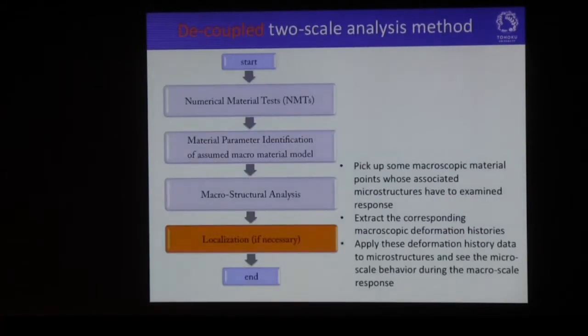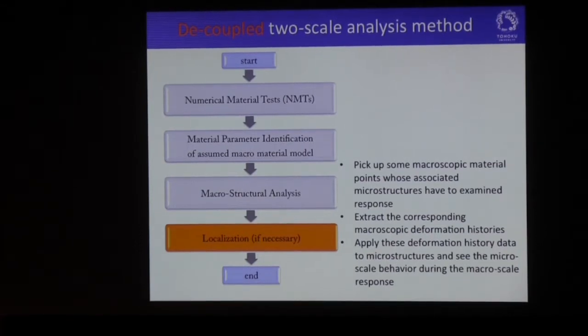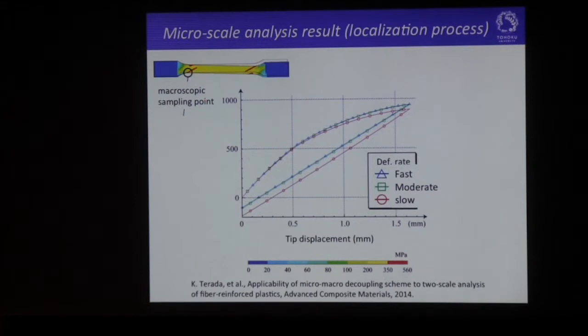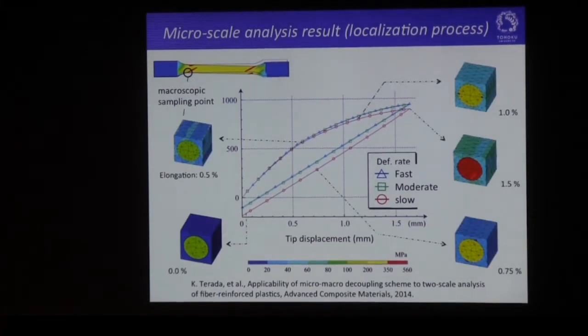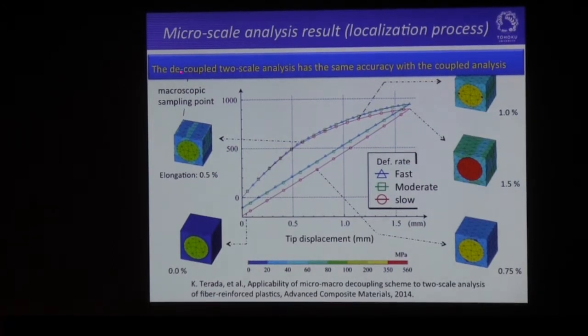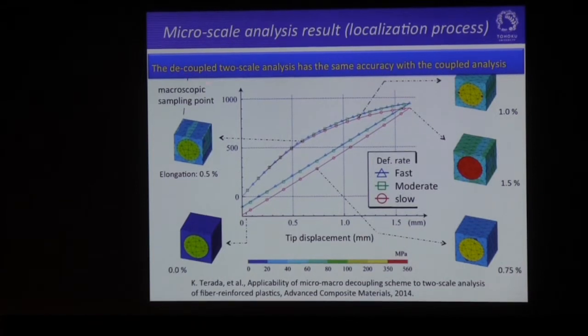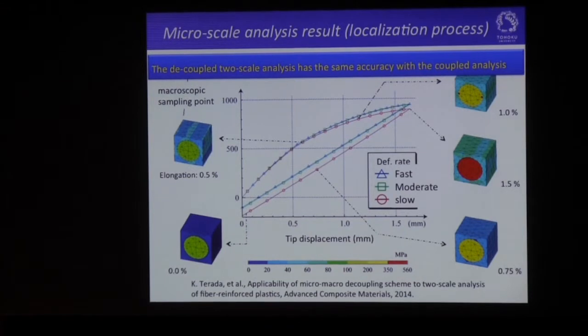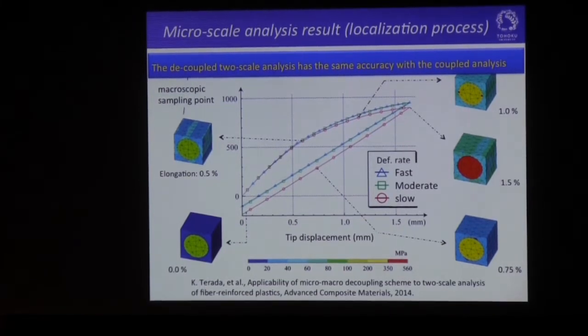So we can move on to the next step, that is localization analysis. That is, we can pick up the macroscopic sampling point here, then extract the macroscopic strain history, then we impose that strain history onto the microstructure to have the microscopic mechanical behavior of the unit cell during this macroscopic deformation. So it can be expected that this decoupled analysis has the same accuracy as the coupled analysis. We expect that. In addition, this decoupled analysis is very cheap compared with the coupled analysis, as you can imagine.